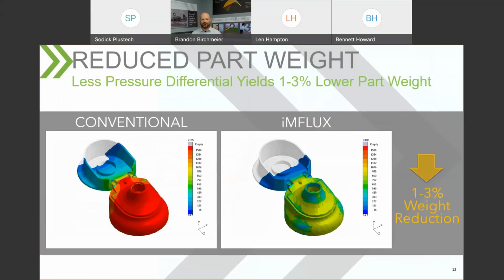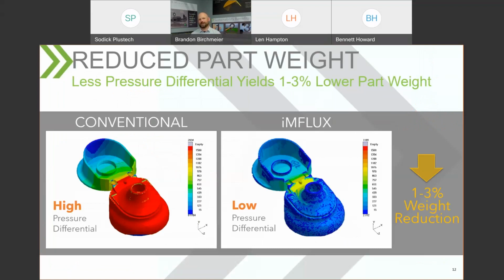So one area of sustainability interest is weight reduction. And here, it's very common for us to get 1 to 3% weight reduction. We talked about that high pressure differential as well in the conventional process. And you can see it even in the simulation side of things, how much more pressure you're seeing on the gate side of that product versus the living hinge side. In iMFLUX process, I am not continuing to pressurize that part at a constant velocity. So those pressure differentials between the lid and the base or the gate side of the part are much more uniform.